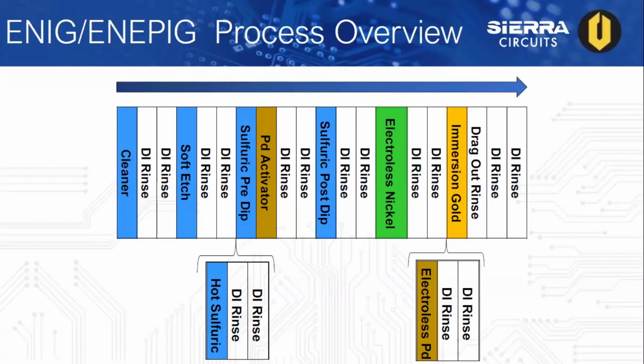Now, the metal deposition is finalized at the very end with the yellow there in the immersion gold, which involves a displacement reaction, where essentially your gold layer is deposited onto the nickel surface and simultaneously displaces nickel ions in solution from the nickel surface layer.